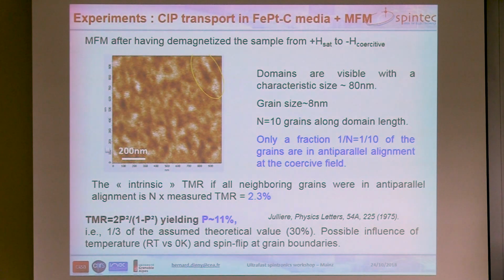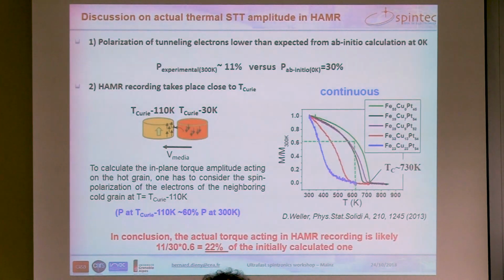So this can be explained by the fact that the theory was developed at 0 Kelvin. Here we are working at room temperature, and we can have also a spin flip taking place in the grain boundaries, which can reduce this polarization of the tunneling electrons.